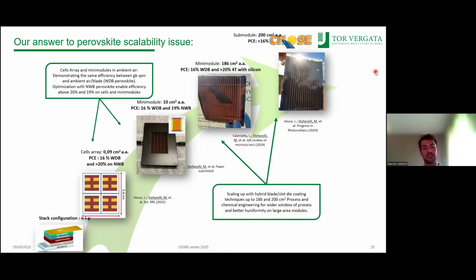So in the end, we started with our NIP configuration, high temperature NIP configuration. We moved to scale first the perovskite from a spin coating glove box to the ambient air with blade coating or slot die coating, and demonstrated practically the same efficiency between the glove box spin and the ambient air for the wide bandgap perovskite. We optimized also the narrow bandgap perovskite with an efficiency above 20% and 19% for small cells and for mini modules. And then we moved forward to scale up with a hybrid approach with blade and slot die coating up to 186 and 200 square centimeters of aperture area modules through process engineering and chemical engineering of our inks.